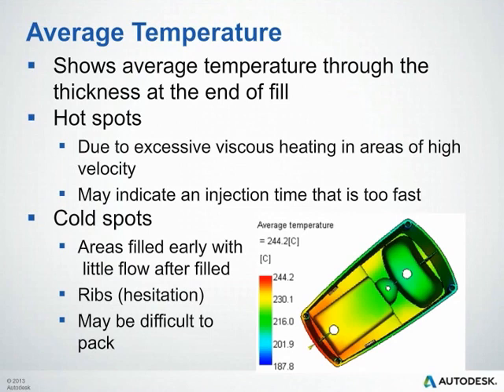The Average Temperature plot shows the average temperature through the thickness of the part at end of fill. What you're looking for here are hot spots or cold spots. Hot spots may indicate significant shear heating, suggesting an injection time that's too fast. Cold spots may indicate areas filling early with little flow after fill, which could lead to packing issues, or hesitation in thin ribbed sections.